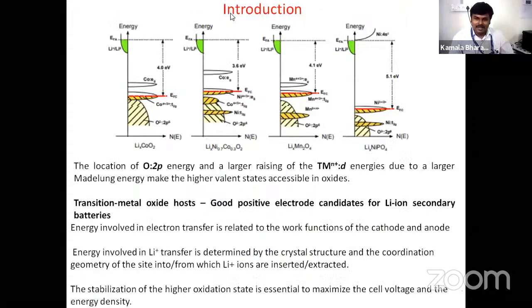Okay, so this band diagram tells you why the transition metal oxide based cathodes are used in the present lithium battery technology. Because of the larger Madelung energy, which makes the higher valence state accessible in the oxide. For example, you see here, for cobalt, the highest redox 4+, 3+ is available for the redox process. So with respect to the lithium redox, we have a 4 electron volt energy window. In the same way, other oxides have a higher electrochemical window. That is the reason these materials are used as a cathode element.